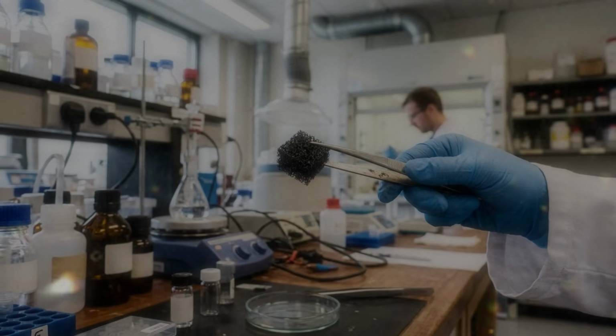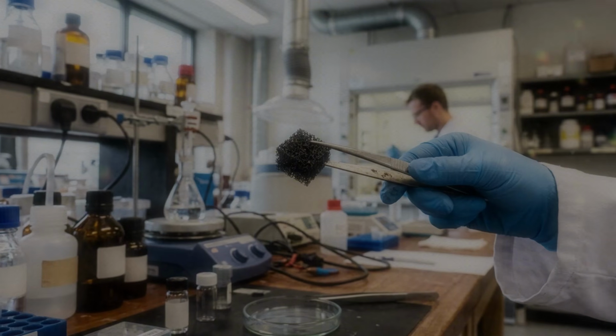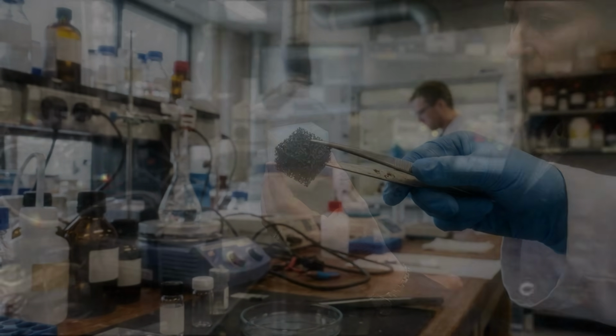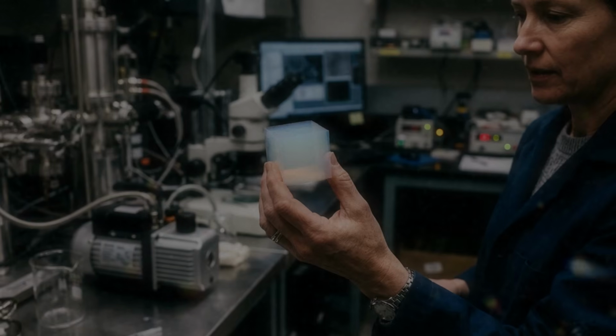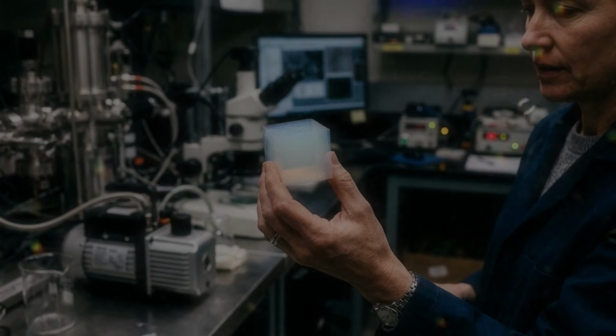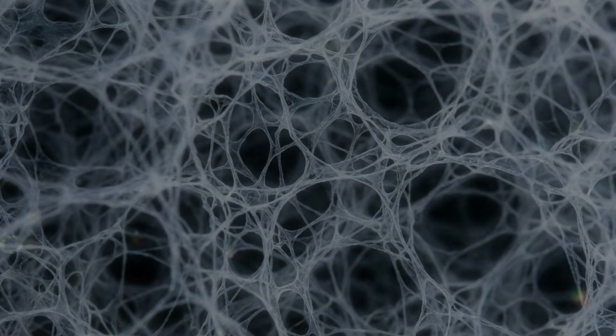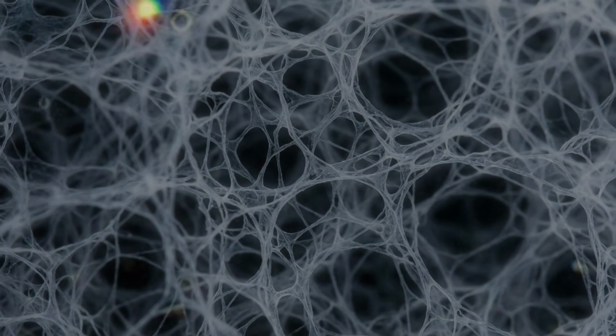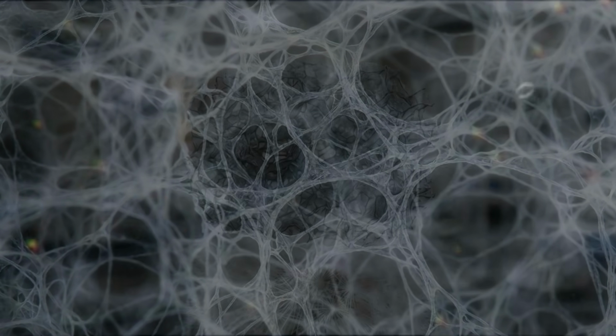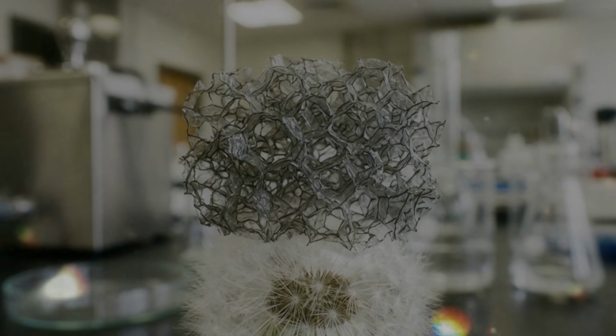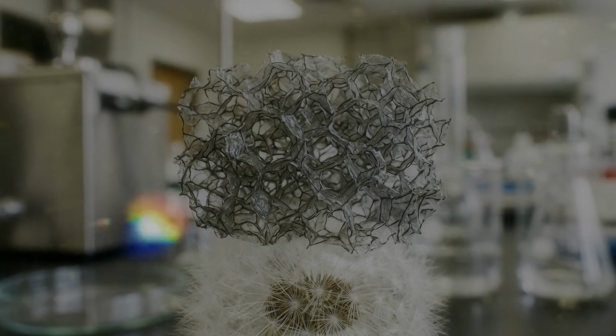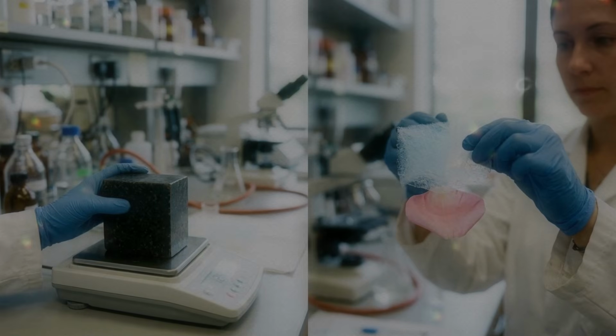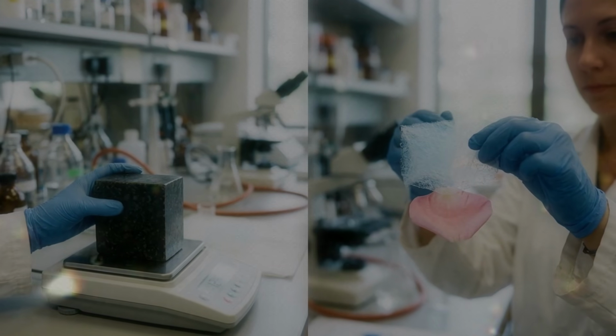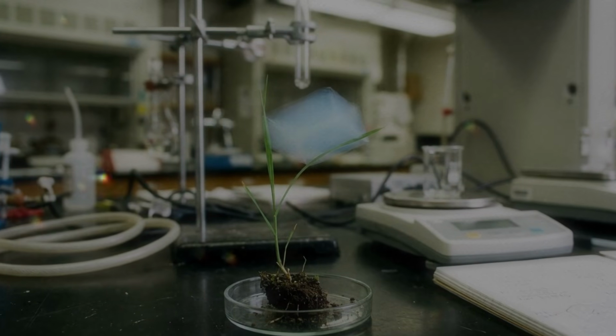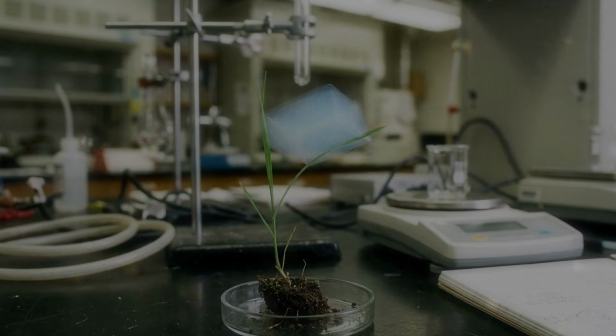This need for consistency explains why researchers study aerogel structure so closely. A photograph of the finished block cannot reveal enough. They examine the pores with microscopes, measure how gas moves through them, test how much surface is available, compress the material, heat it, and track changes in electrical behaviour. Each test reveals a different part of the architecture. A microscope shows shape, a mechanical test shows how forces travel. A conductivity measurement reveals connected paths. An absorption test shows whether liquids can enter. A thermal test shows how energy moves.